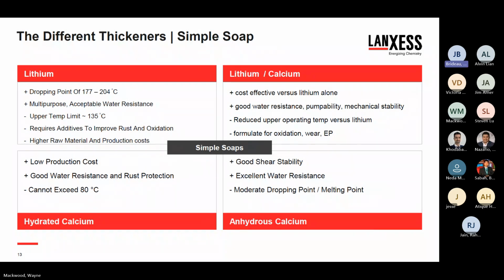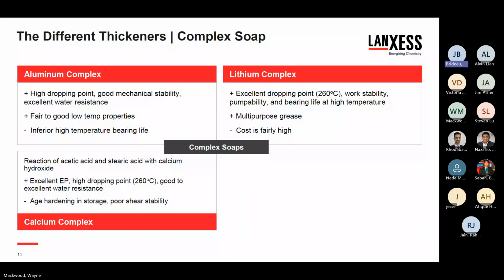On the complex side, we add additional complexing agents to increase the upper operating temperature limit of the products. The most common ones are aluminum complex, lithium complex, and calcium complex. I think calcium complex has faded to a large extent. It's not used very often. But aluminum complex is very big in food processing and in mining. It has a good high dropping point, good mechanical stability, and very good water resistance. It's also used in steel. But really, the workhorse in this space is the lithium complex. It is an all-around excellent grease, with a very high dropping point, good mechanical stability, good pumpability, and good bearing life at high temperatures, well formulated. These are very good high-temperature operating greases, and they will be seen in a range of applications.